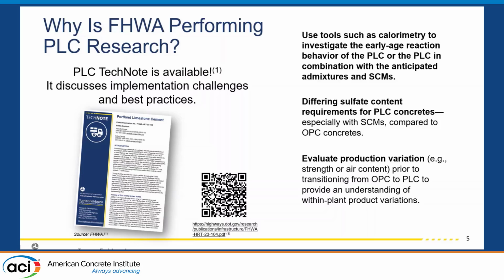Some of those best practices include using tools such as isothermal calorimetry, which was already talked about a lot, which is great. I'm going to talk about it some more, so we're all in agreement there. This can help you investigate your early age reaction behavior in your PLCs, and additionally with your PLCs in combination with SCMs and admixtures. There's also differing sulfate content requirements for PLC concretes, and we'll talk about that more. And then evaluating your production variation, first in your OPCs before you make that transition. For some of you, it's already a little too late. But understanding your production variability before making this transition will really help you understand what to expect when you make that switch.